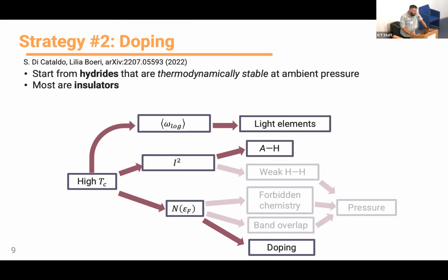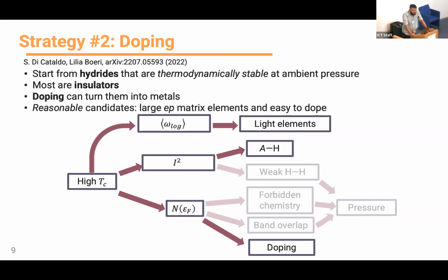Now, what I want to focus on much more is the alternative strategy. So let's say we want to get rid of pressure entirely. We don't want to reduce it. We really want to get rid of it. So we have to start from hydrides that are already thermodynamically stable at ambient pressure. But essentially, most of them, we know them to be insulators. And what we are left with in this diagram is we lose a lot of options. We have to use bonds between a different element and hydrogen. And we have to use doping to make our structure metallic. Now, the idea is that doping is very difficult to do in experiments. So we really want to start from reasonable candidates.